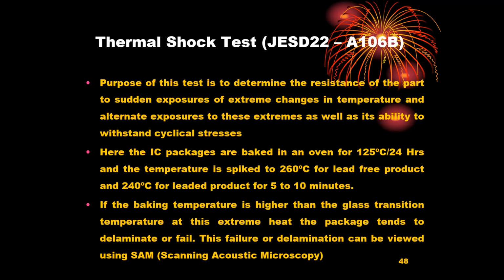If the baking temperature is higher than the glass transition temperature at this extreme heat, the package tends to delaminate or fail. So the influence of glass transition temperature on delaminations was pretty strong compared to many other criteria.